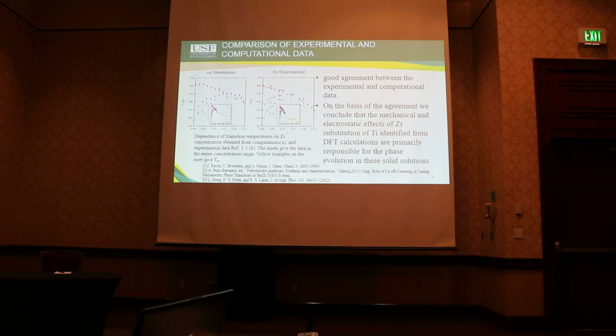So here we have a comparison between the dependence of the transition temperatures on the concentration of zirconium, comparing the simulation and the experimental. We find excellent agreement between the computational and the experimental data, which leads us to conclude that the mechanical and electrostatic effects that were discovered from the 0 Kelvin simulations are primarily responsible for the phase evolution in BZT and these solid solutions.